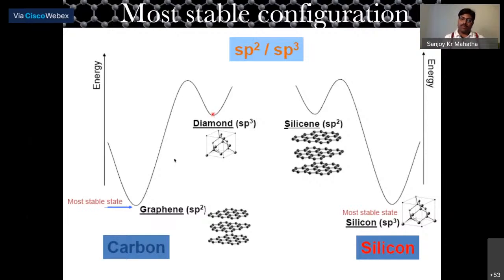Okay, so that's why we get a lot of graphite in nature rather than diamond. But in the case of silicon, it's the opposite. The sp3 hybridized configuration is the most stable one, whereas sp2 hybridized is a metastable state. That means even if sp2 hybridized silicon exists, we need to prepare it in a very special condition, and this will be metastable in nature. Metastable means if there is any kind of excitation available, the whole structure will melt or transform into sp3 structured silicon.